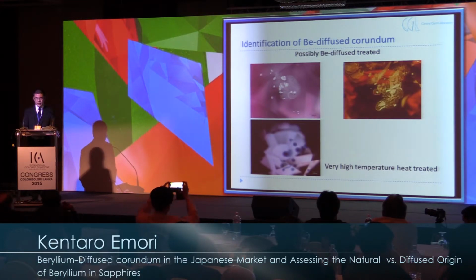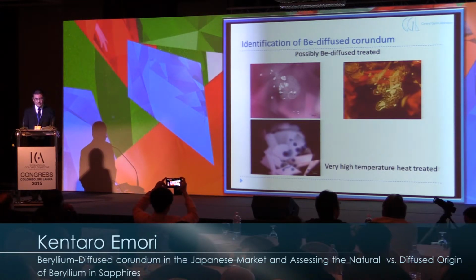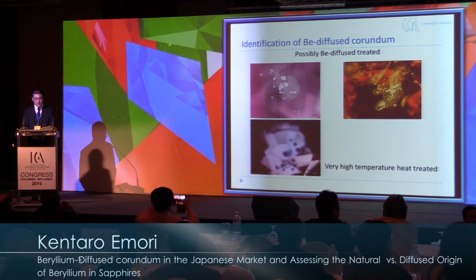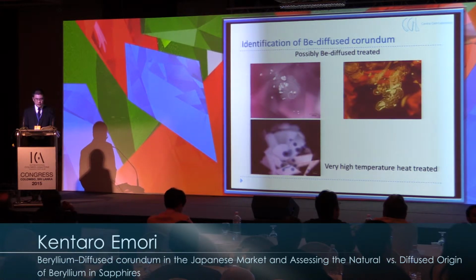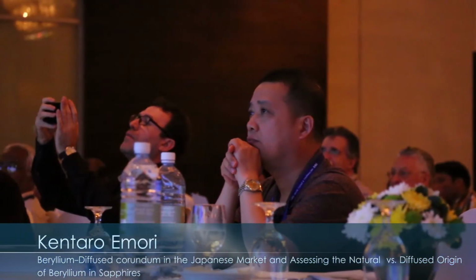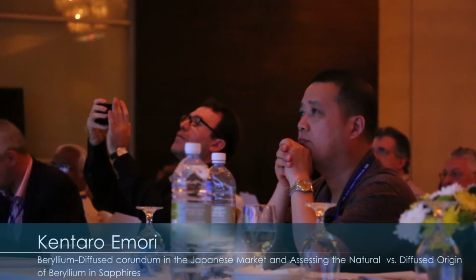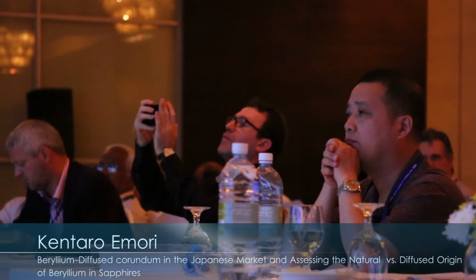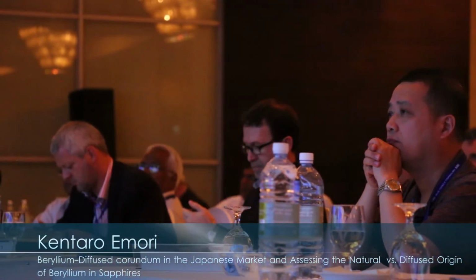High temperature heating does not always mean beryllium-diffused treatment, but beryllium diffusion treatment is suspected. Inclusions in these photos suggest the corundum was heated at high temperature. In general, beryllium-diffused treatment is undergone at high temperature, so careful observation of inclusions is important, which suggests high temperature heating.